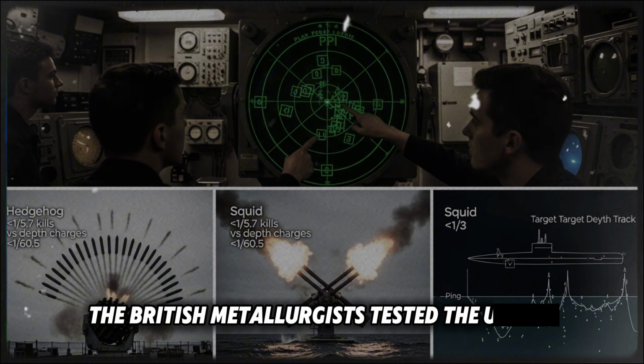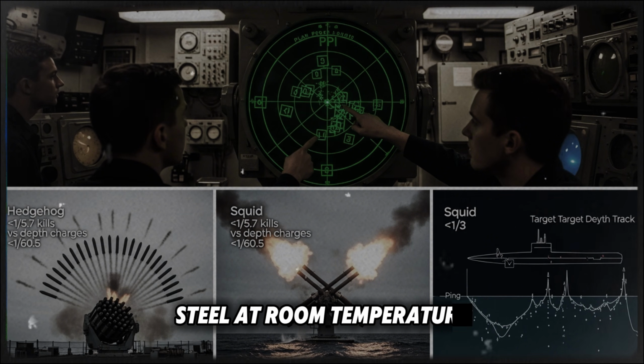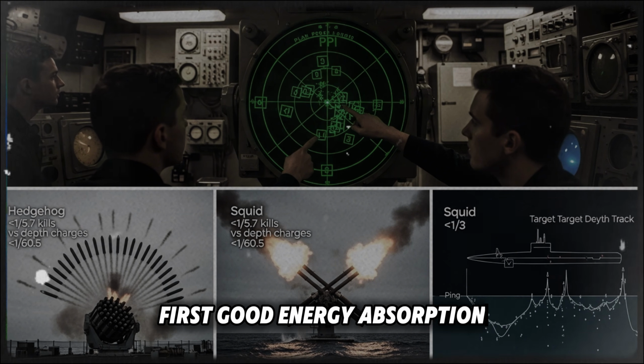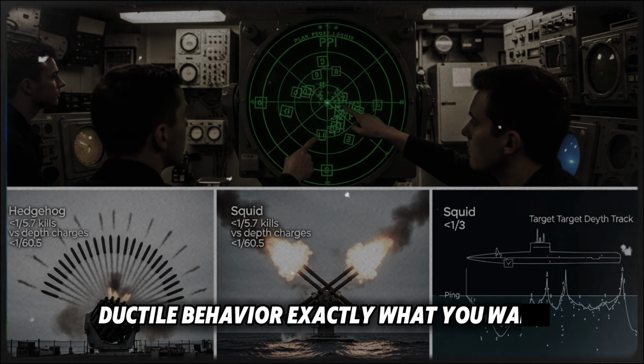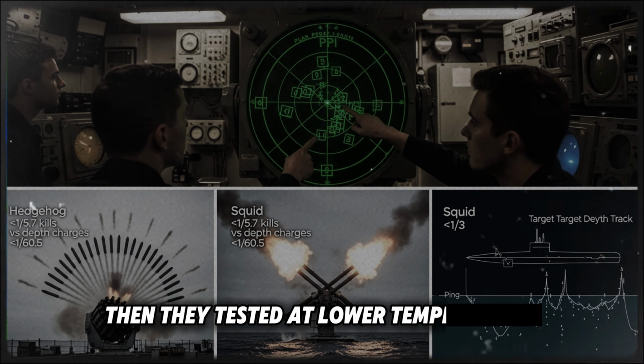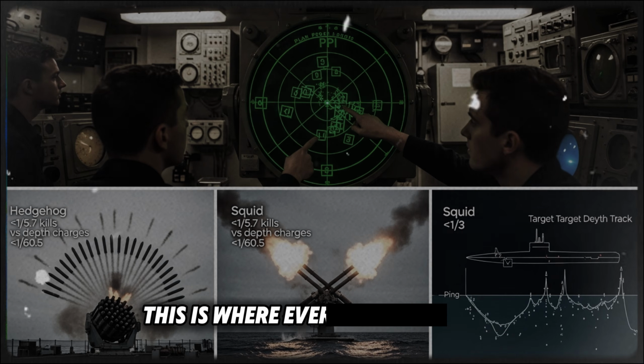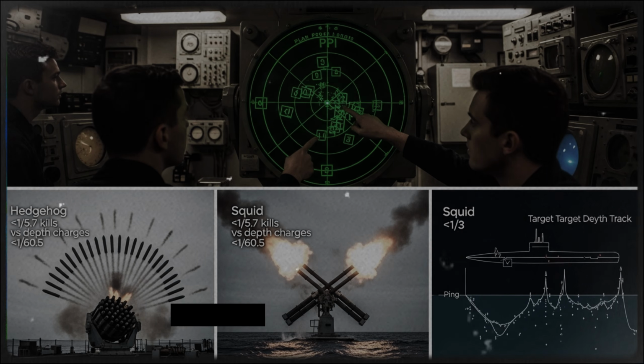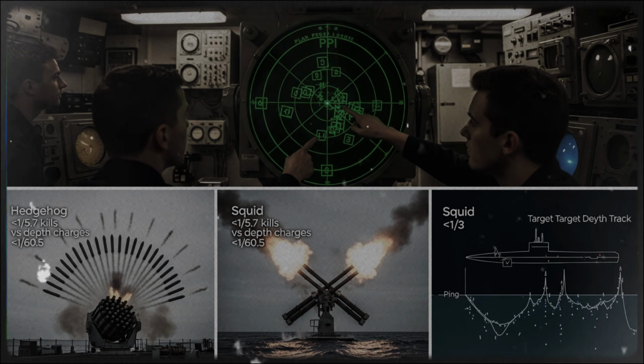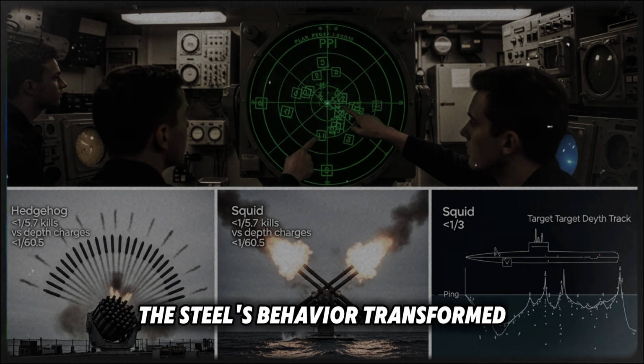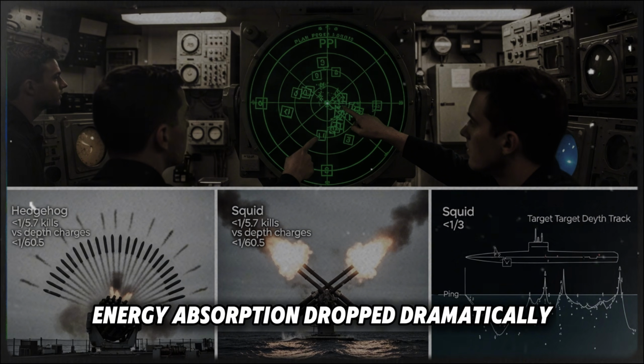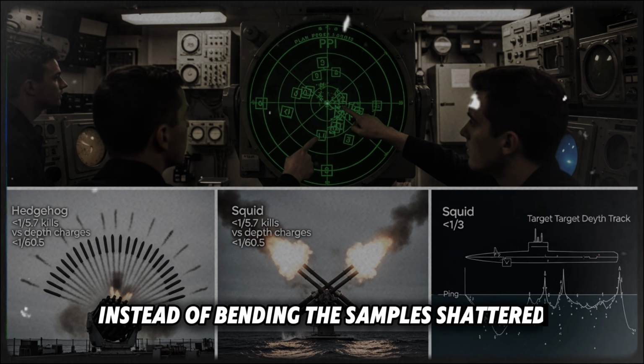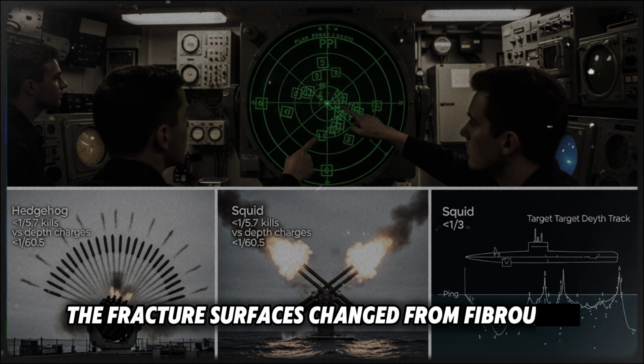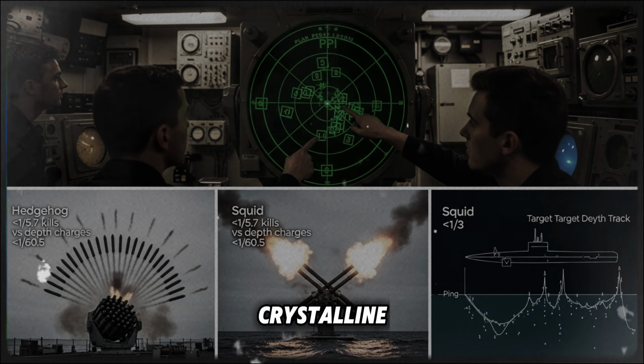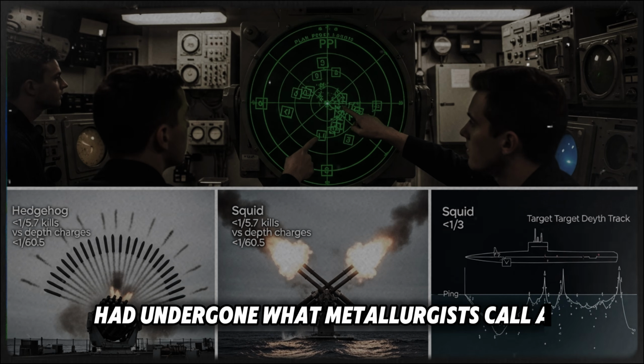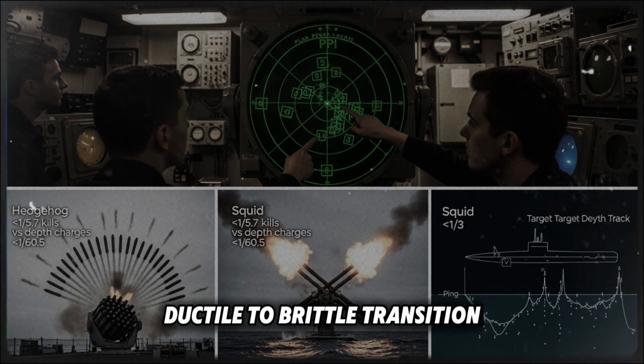The British metallurgists tested the U-boat steel at room temperature first. Good energy absorption, ductile behavior, exactly what you want. Then they tested at lower temperatures. This is where everything changed. At around 5 degrees Celsius, the steel's behavior transformed. Energy absorption dropped dramatically. Instead of bending, the sample shattered. The fracture surfaces changed from fibrous to crystalline. The steel had undergone what metallurgists call a ductile to brittle transition.